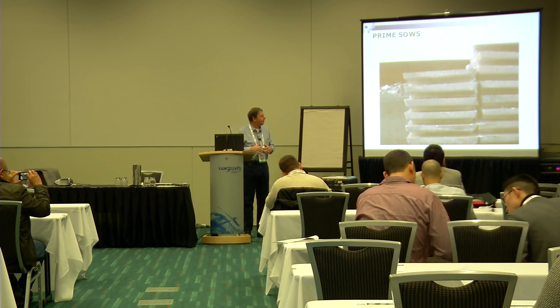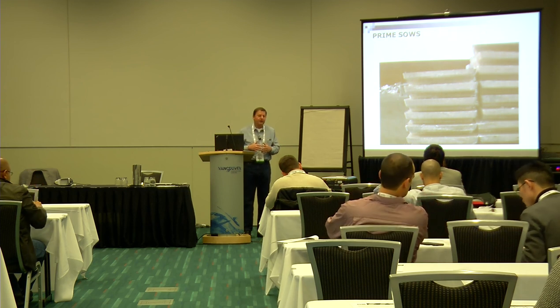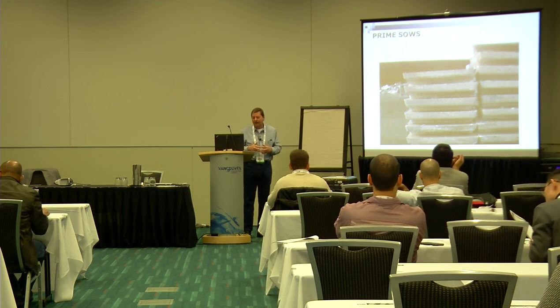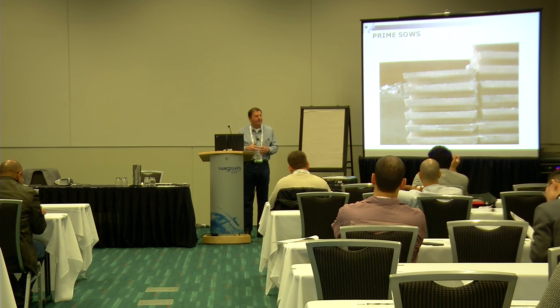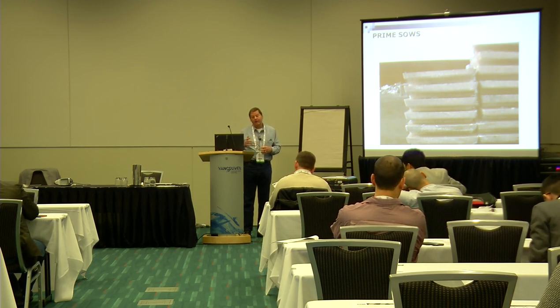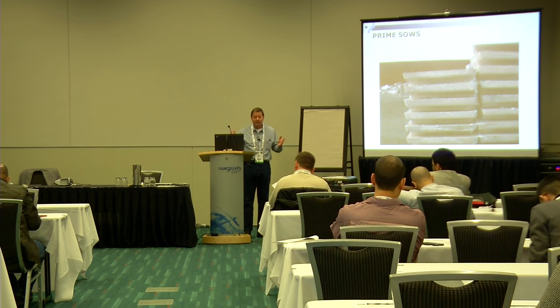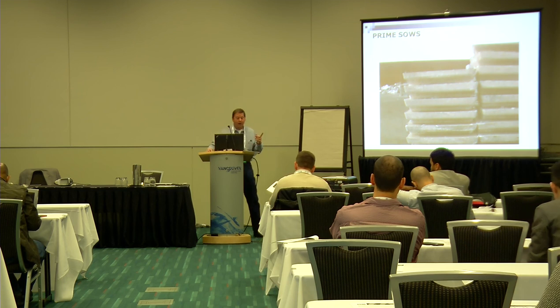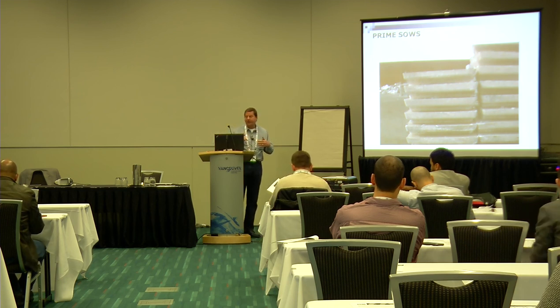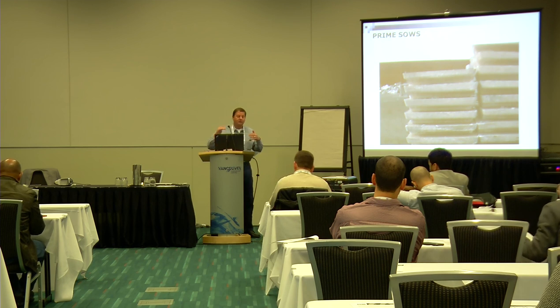This is what's called a primary sow. This is coming from companies like Alcoa or Kaiser, and these are 99.6, 99.7% aluminum with a balance, and they're only talking about 0.3 left, so talking about silicon and iron. The primaries use a lot of it. In our billet operation, we use a lot of it because of what we're making, because we have no tolerance for too many other elements.